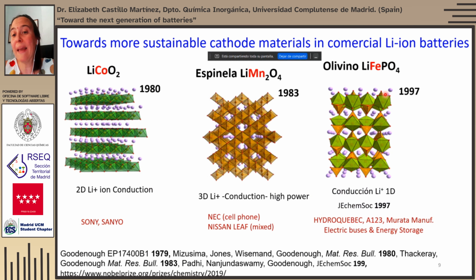On the other hand, the even more friendly lithium iron phosphate, which was developed also by the group of Professor Goodenough, but this time at the University of Texas at Austin, has an olivine type structure where only one-dimensional tunnels for lithium-ion diffusion are there. This imposes some more limitations on the material, both ionic and electronic conductivity, but this can be overcome by properly nanostructuring the particles so that the tunnels where the lithium ions have to diffuse are along the short direction in platelet-like particles, and also by carbon coating the nanoparticles.